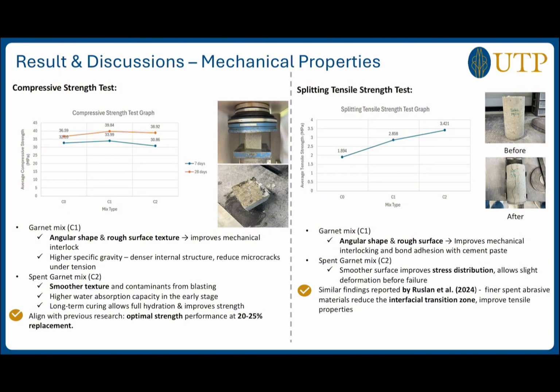And for the spent garnet, its strength is reduced a bit compared to the garnet mix because of the smoother texture and contamination from blasting. But it is still acceptable because it achieved our target compressive strength, which at 28 days is 30 MPa. And next is the splitting tensile strength test.